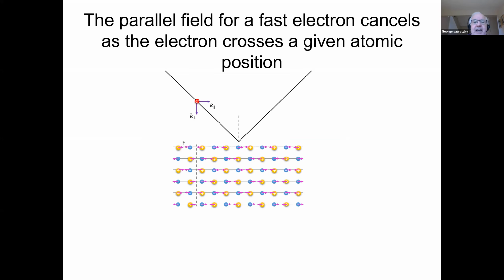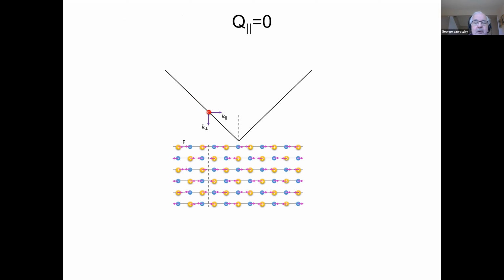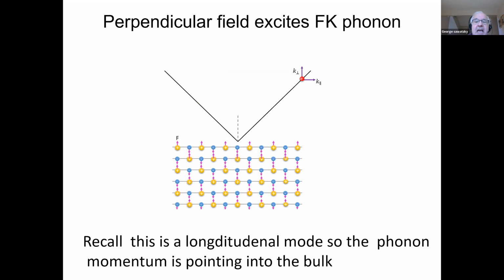So if I just look at a material and have an electron coming in at fairly high speed, coming in like this, then as it crosses, its electric field in the perpendicular direction would be pointing in that direction, but there's a horizontal field, and it is oscillating. It is pulling that atom to the left here, and when it passes it, it'll pull it to the right. And because it's going fast, it averages out, because the atom doesn't have time to move that quickly. That's seen here, the arrows change, right? If you now go to the end, way out here, all you have left is that you've left behind a time-dependent perpendicular field, right? And that time-dependent perpendicular field is the one that excites that phonon. If you do a Fourier transform of that, it has that frequency component in it, and it will excite that phonon. It has a very strong coupling to it.